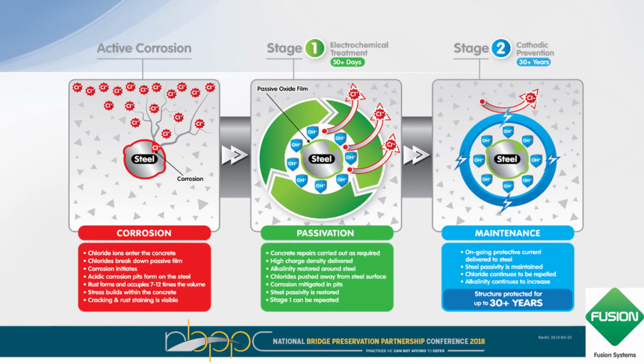This just gives you an idea of how this works. You have basically the active corrosion that is occurring. We've heard a lot about that this week. Stage 1 is the electrochemical treatment phase. So that's the passivation phase. And the idea is that you're pushing the chloride away from the bar, but you're also generating hydroxyl ion, OH, at the bar, which is increasing the alkalinity, lowering the chloride content just around the bar, in order to passivate the steel. Now, the amount of current that's provided in this phase is really dependent upon the amount of chloride contamination you have.